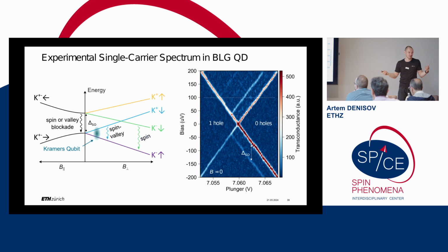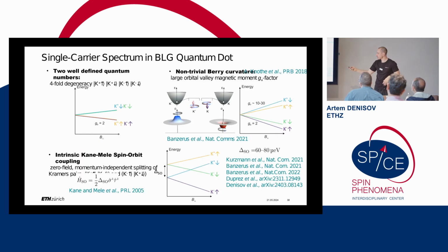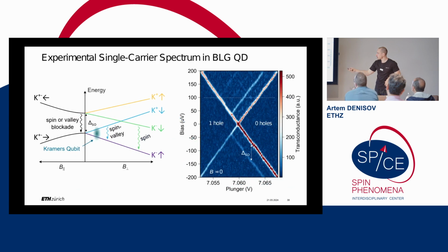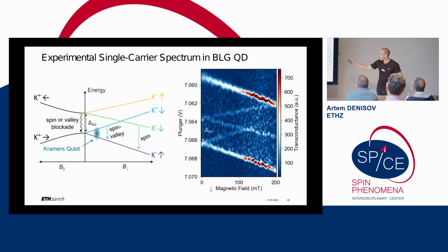Okay, so the previous slide can be a bit theory heavy, spin-orbit coupling, Berry phase. But as an experimentalist, I believe in it because I can just see it every day in the experiment. I make a device, I tune it to the 0 to 1 hole or electron transition. At zero magnetic field, I see what I should see: I see a ground state and just a single excited state. Then I do finite bias spectroscopy, meaning that at finite bias, I continue measuring conductance as a function of magnetic field. And what I see is exactly that each of the states is not a single state, it's a doublet which splits as a function of magnetic field with a very high G factor as expected. And you can literally just map your experimental data to your theoretical spectrum immediately.